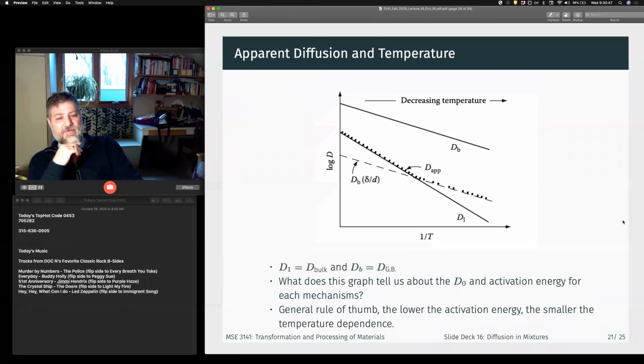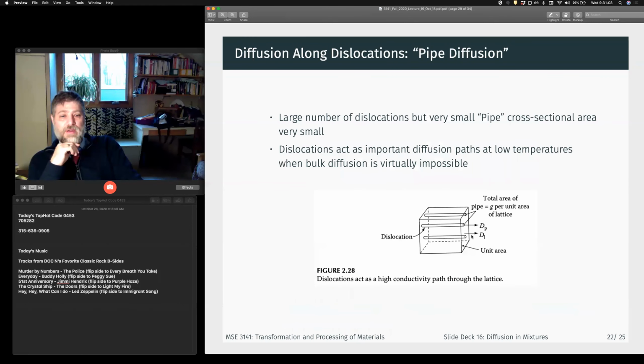And that basically tells us that at very low temperatures, the only diffusion that we're going to have is along grain boundaries or surfaces. Bulk diffusion is effectively going to be completely shut down. We also have diffusion along dislocations, and this is called pipe diffusion. Dislocations can act as important diffusion pathways at low temperatures when our bulk diffusion is virtually impossible. But we need a very large number of dislocations, because the cross-sectional area of each dislocation pipe is very small. So it's just another important short circuit path. If you hear the term pipe diffusion, that's what this means.